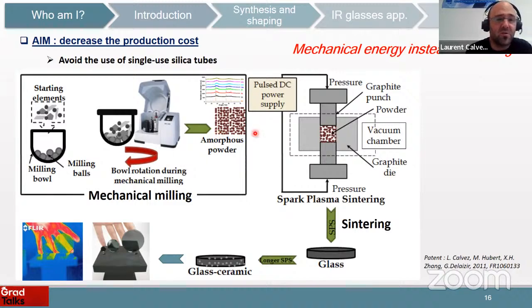So instead of heating, just by grinding the elements for several hours, you can get the same composition, the same glass. It's only powder, so then you have to make a bulk glass. And we decided to use something which is pretty new, which is spark plasma sintering. So you heat the powder and press it at the same time, and also use pulse current to make it faster. So you sinter the powder, and at the end you get a glass.